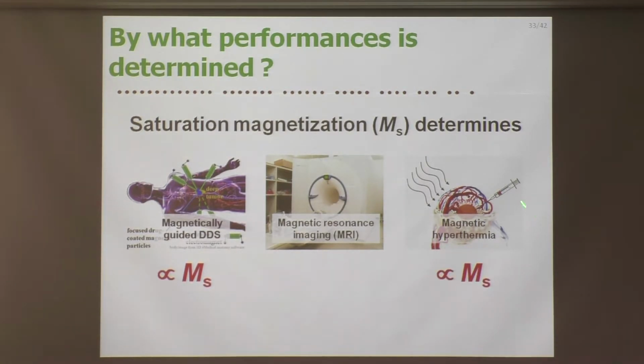The situation is the same for magnetic hyperthermia. In the case of MRI, the effect of saturation magnetization is even bigger—performance is proportional to the square of the saturation magnetization.